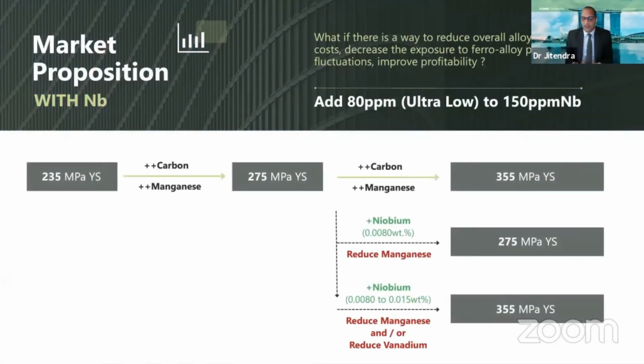So the proposition in this particular case is ultra-low niobium. What I'm talking about with ultra-low niobium is niobium additions of what I'm terming 80 to 100 parts per million, so 0.008 to 0.01%. And this is what we're terming ultra-low.